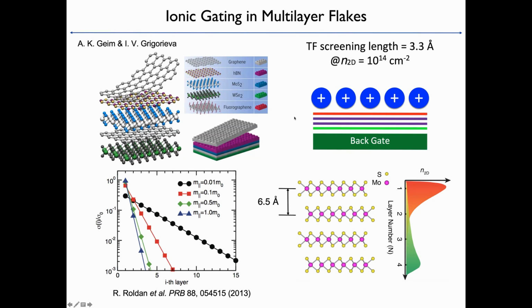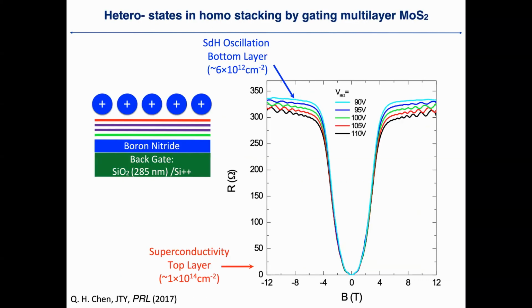But then, with this technique, you can gate the top layer, and again you can gate from the bottom layer. And if they are well separated, for instance only a few layers, you can make a very isolated parallel conduction channel. And this is slightly different from the idea of stacking of multilayers. Here, we only use a natural stacking, but we paint the electronic structure by gating. So you can paint them into different states. One is in the metallic phase, and the other can be in a superconducting phase with different gating. And this is quite clear in a system with this kind of configuration. So we can gate from the top and gate from the bottom.